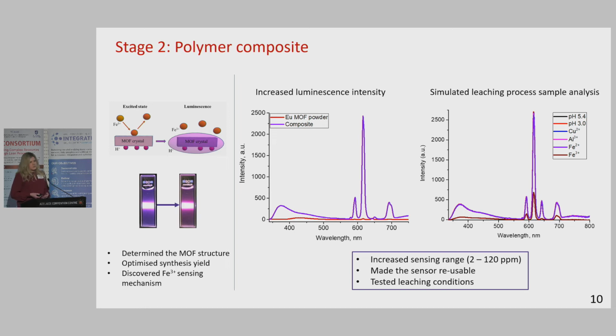As a powder material, this MOF senses up to 4 parts per million of iron 3, while as a composite, it could sense up to 120 parts per million. It also made the sensor reusable, and we started testing out simulated leaching conditions to see how decrease in pH and presence of other metal ions would affect the sensor. And we found out that only iron 3 causes decrease in the intensity of light emitted by our sensor.